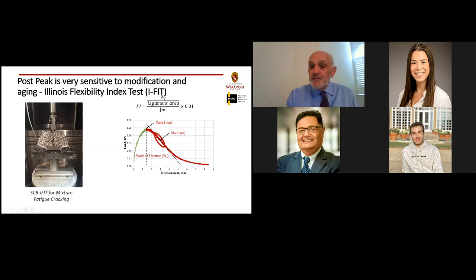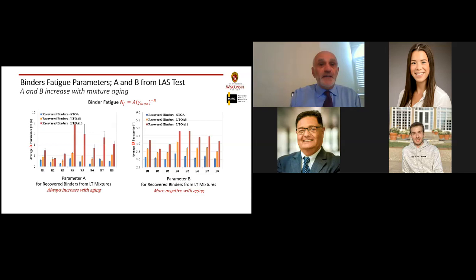So we did our LAS test, the binder fatigue. And here are the A values and the B values, from the fatigue law. You can see we get very good distinction between the A values and the B values. Certainly the A value, which is dependent on the strain sweep, which includes the very high strain levels that I'm after, differentiates between the binders much better than the B, which is measured at 1% strain, very small strain.